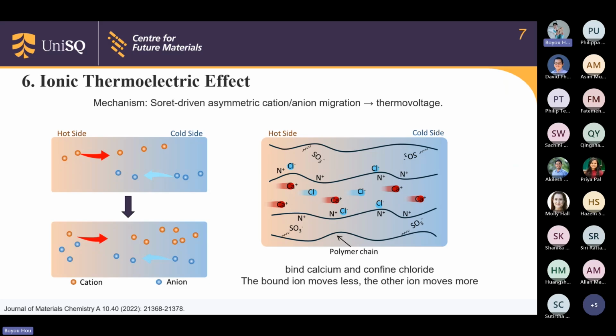The bound ions move less, and the other ions move more, and the Seebeck coefficient increases. Because the effect is driven by entropy, it can give a large voltage even at small temperature differences. With good encapsulation, the response is repeatable outdoors.